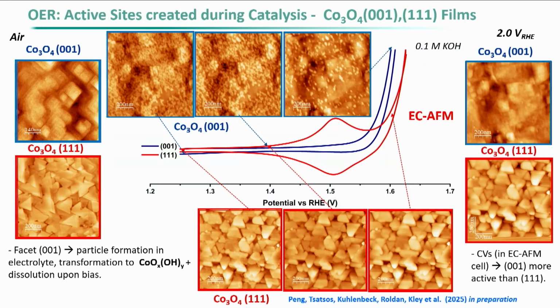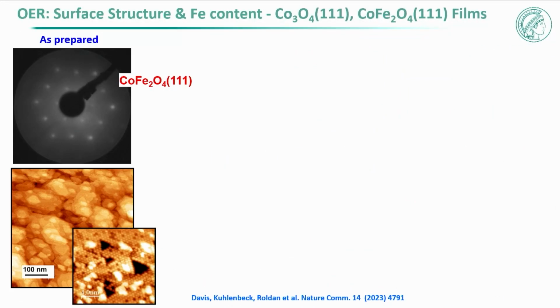And when I have this data, then I can go back and say, I'm going to try to design my electrocatalytic material, my nanoparticle, maybe with more preferential orientation here, even though we know that it's going to have certain modifications during the reaction. So the other thing was that since I know that the iron impurities are doing something, I can try to put the iron already in the exact amount in the precatalyst.